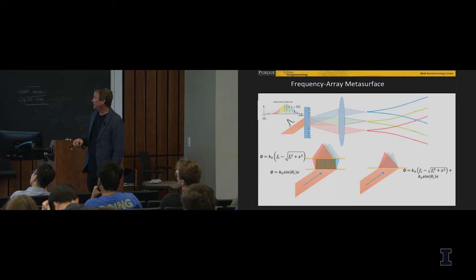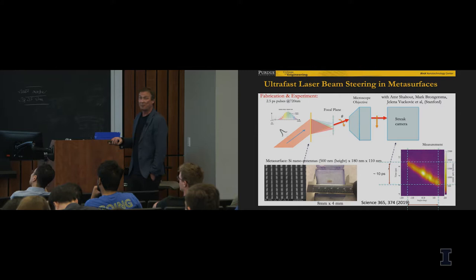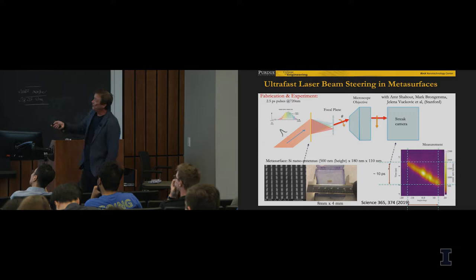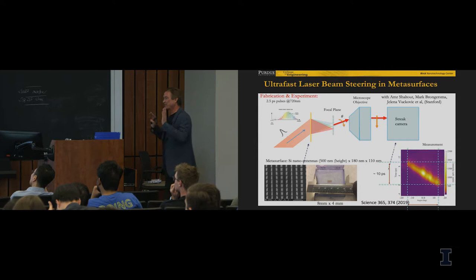It's a simple silicon-based metasurface, absolutely nothing special, very simple fabrication. Here are all the parameters. So you send the light. This is the focal point where you have this virtual frequency array metasurface. And then you image with the streak camera. And indeed, you see that within 10 picoseconds, the position of the beam goes from minus 15 to plus 15 degrees. And you could control it. You could increase the range of angles. It just comes down to design.